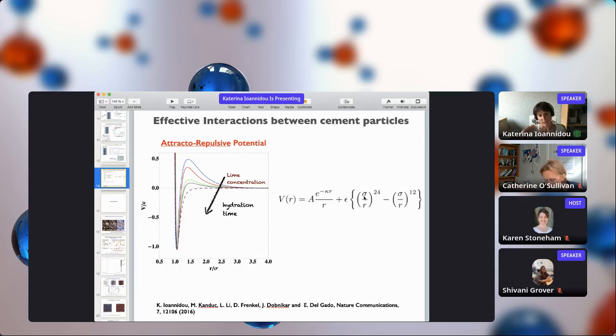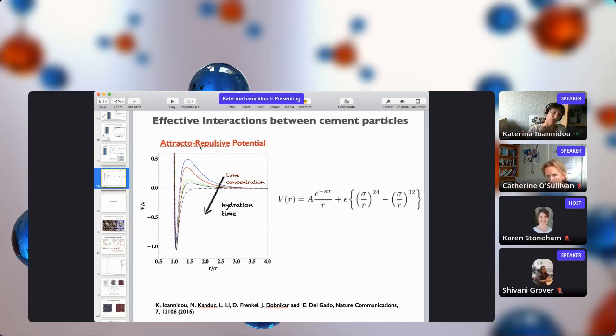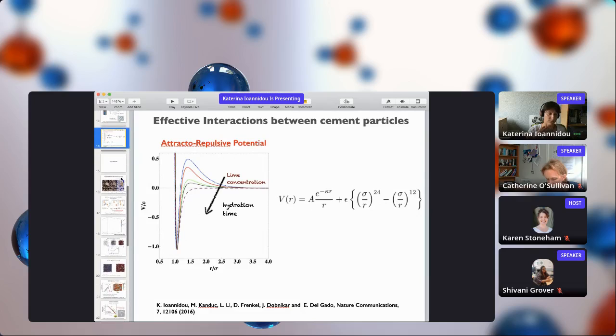Usually it's 6 and 12, but here we have 12 and 24 to get the right well for the CSH, and we have a Yukawa potential that creates this repulsive shoulder. By tuning the energy parameter of the Yukawa and the energy parameter of the Lennard-Jones, we can control how much attraction and repulsion we have in the system.